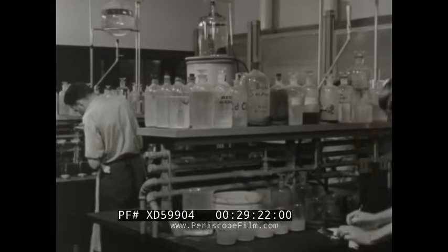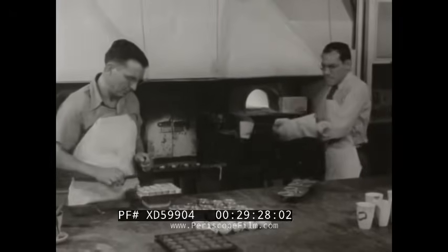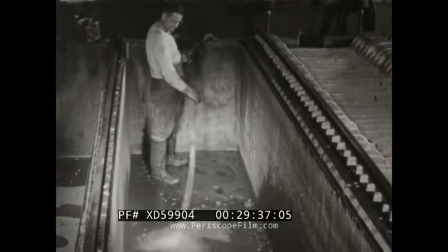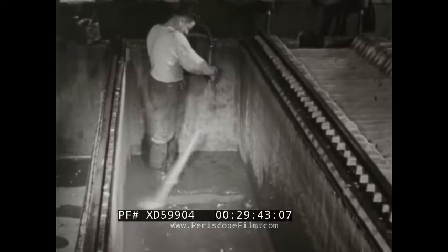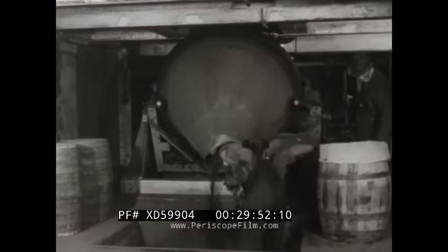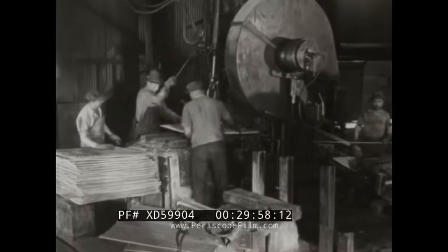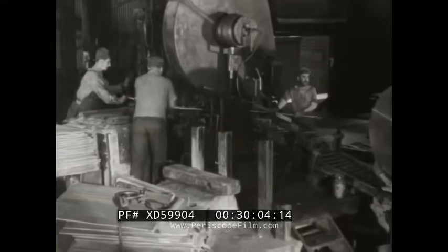Strict laboratory control is exercised throughout the entire cycle of operations from the mine through the mill, smelter, and refinery. The slimes are slurried from the bottom of the tank. They are first leached to remove any remaining copper, then filtered, dried, barreled, and shipped to another refinery where their gold and silver content are recovered. Some of the copper cathodes are sent to the shearing department where they are cut into sizes required by the United States Mint or by brass foundries.